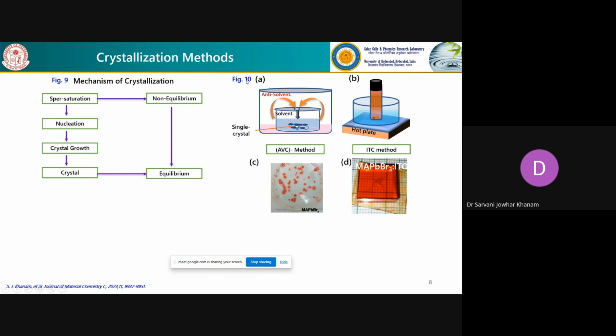As seen in figure 10, two methods are most well known in the literature: the anti-solvent method and the hot temperature crystallization method, the inverse temperature crystallization method. From the anti-solvent method, we get small crystals, which are not suitable for higher energy radiation detection. To stop the incoming higher energy radiation, we need a larger surface area, which can effectively collect the charges, and we will be able to see the signals. So we have selected only the ITC method.